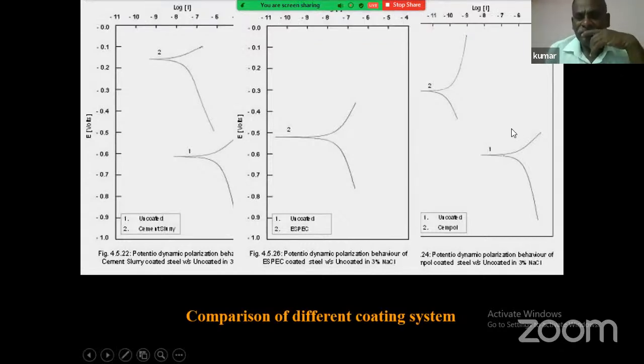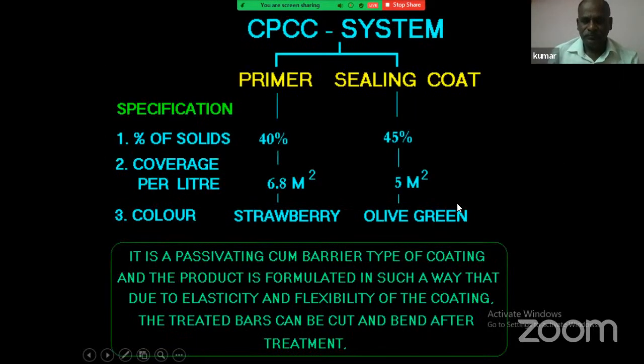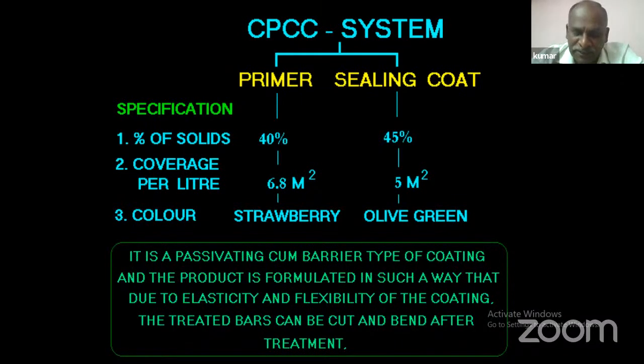When you are seeing here, that is CPCC. This is your uncoated bar, this is the coated bar, much lesser than the uncoated bar. The corrosion rate is much lesser. So in that case, this has both barrier as well as protection. So this is the mechanism incorporated while developing this system. This system was developed at CSIR CECRI during 88 to 93, patented in 93, and released for usage in 97.